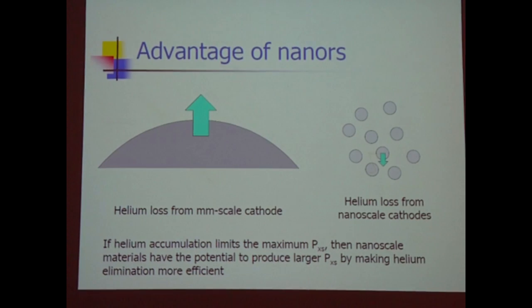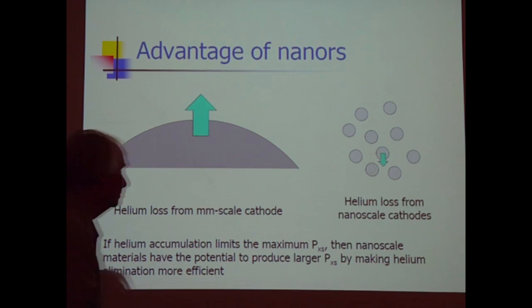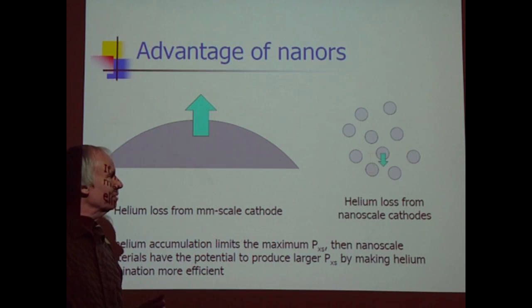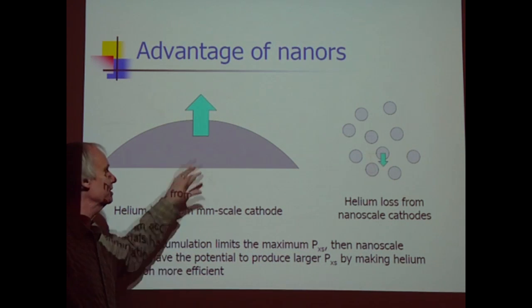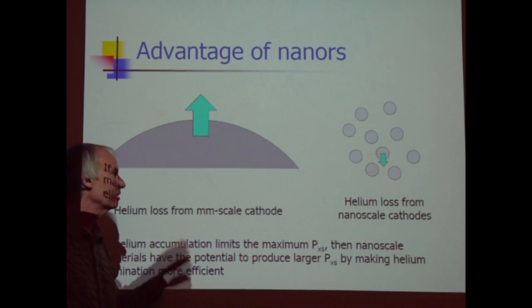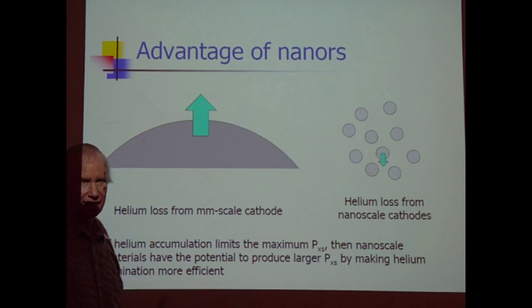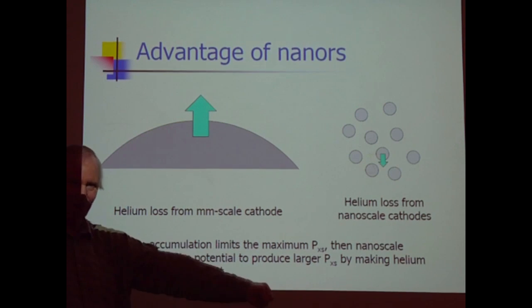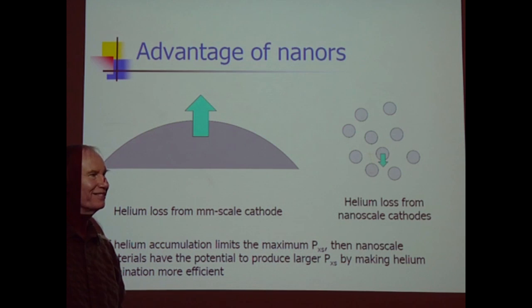But this may be a very basic question: how can helium be taken out when it's in a nanostructure? And also, how small does that nanostructure need to be? At the level of the argument today, in terms of size, there's a simple scaling that the excess power is going to go by the inverse size scale length if it's diffusion dominated. So basically, making it smaller helps, making it even smaller helps. I'm going to leave it to Mitchell to talk about his experience with respect to how well these things work as a function of size, if he chooses.